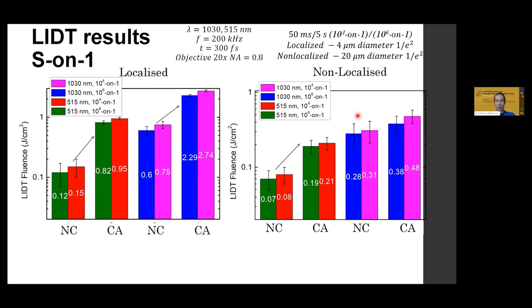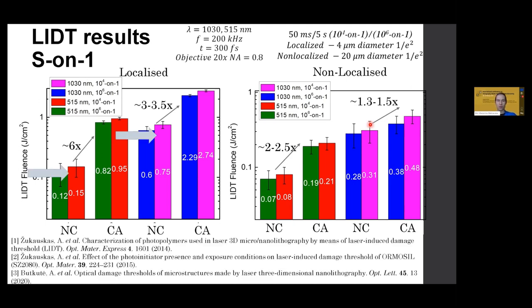So for inorganic ones, whether short or in small spot or larger and longer durations, visible or near infrared wavelengths, actually the difference is not the same. For some cases, it is improved up to 6 times. For some, it's like 3 to 3.5. Or for non-localized, it gets lesser. It's slightly reduced to 2 and less than 2 times, like 1.5 times. But in principle, in all cases, the calcination or the production of inorganic lenses is beneficial for the damage threshold.